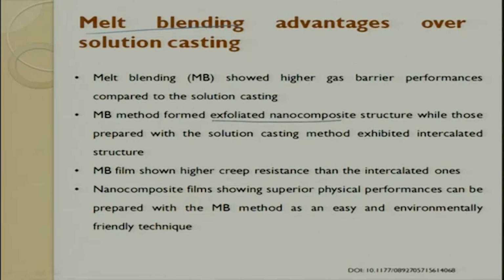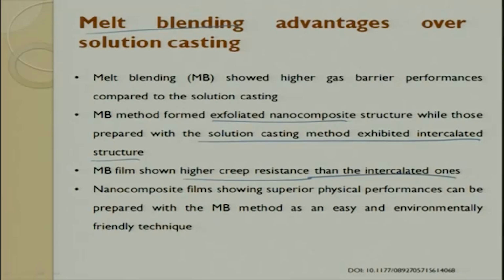Here it forms an exfoliated nanostructure, while those prepared with solution exhibit intercalated structures only. So it is much more stronger than solution casting. The melt blending film shows higher creep resistance than the intercalated ones.